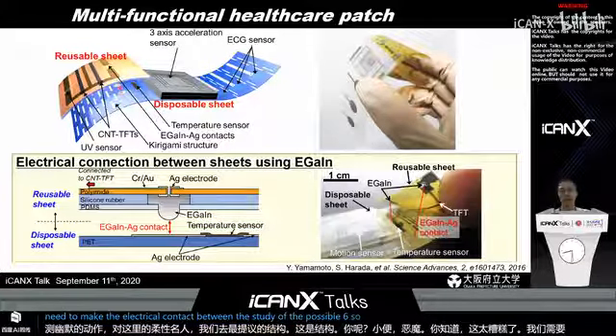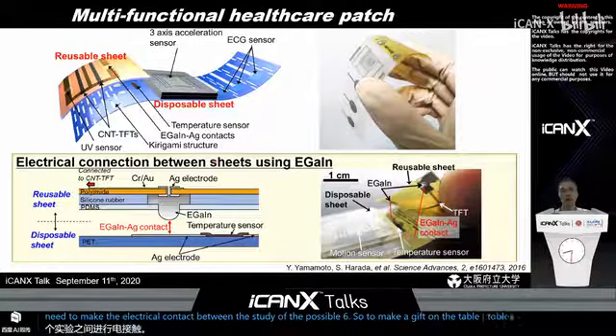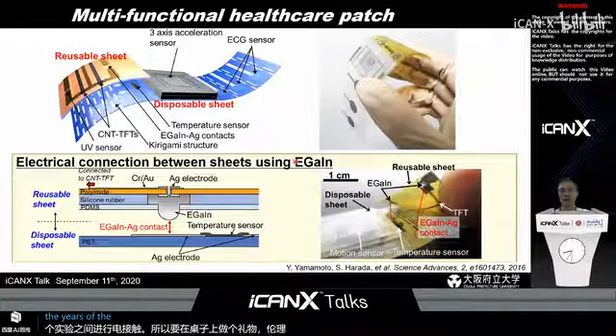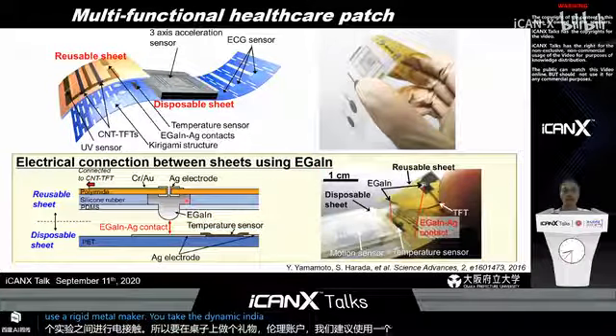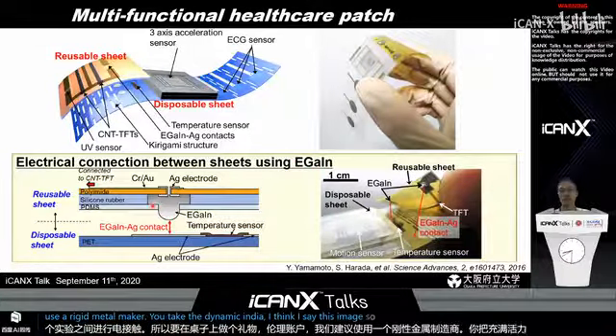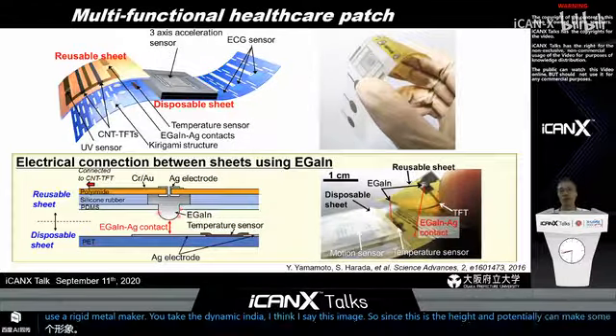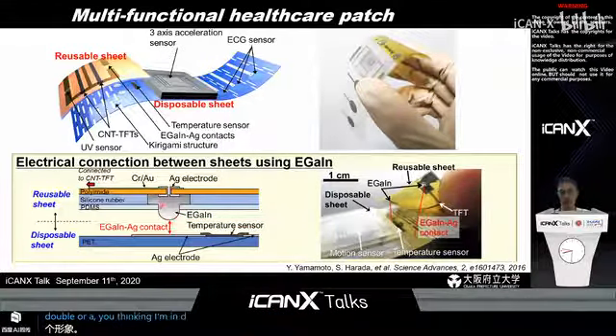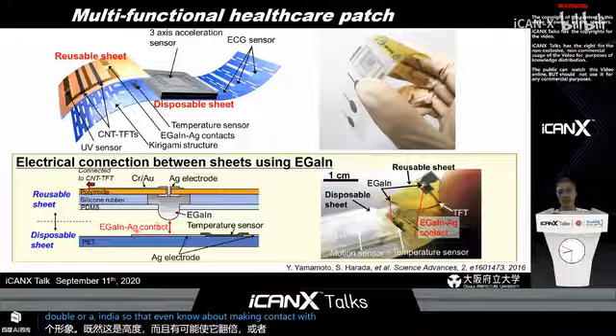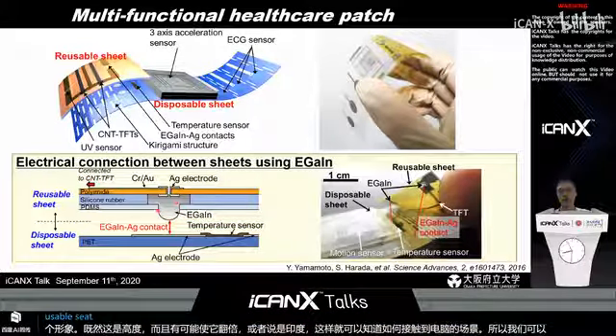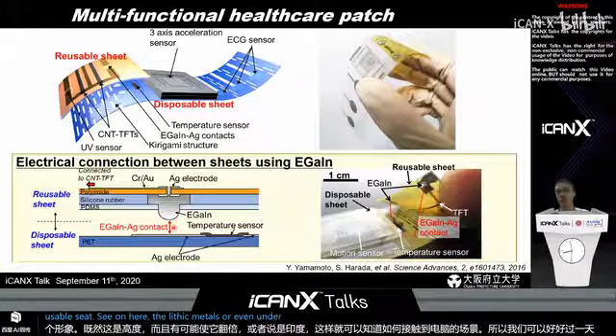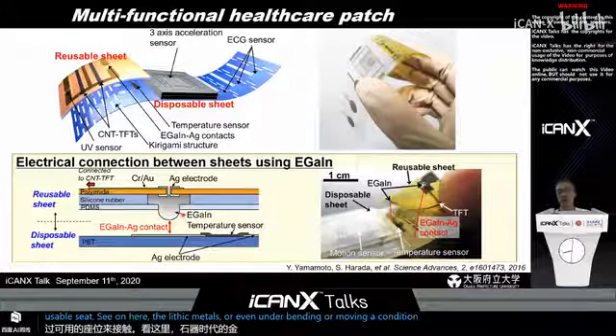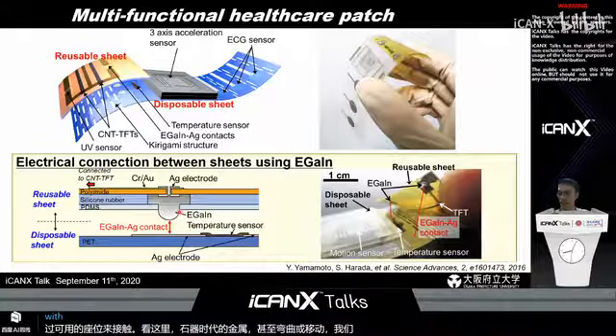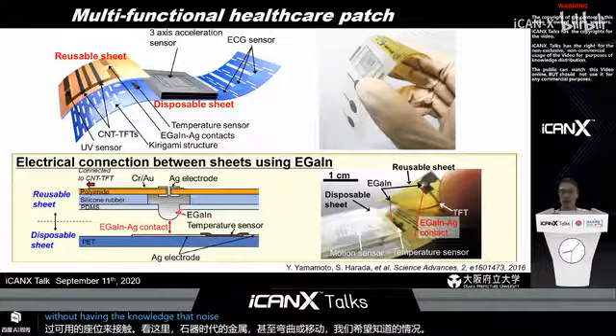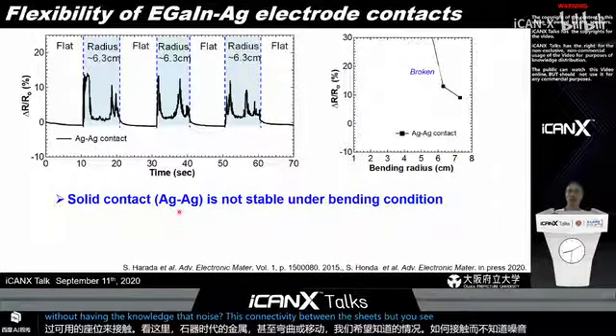So to make a good and stable electrical contact, we propose to use a liquid metal like eutectic gallium indium, as you can see in this image. Since it has a high surface tension, we can make a ball of the eutectic gallium indium, so that even after making contact to each sheet, we can make a good electrical contact to the reusable sheet. And also, since we use a liquid metal, even under bending or moving conditions, we expect to have a good electrical contact without large noise or disconnectivity between the sheets.